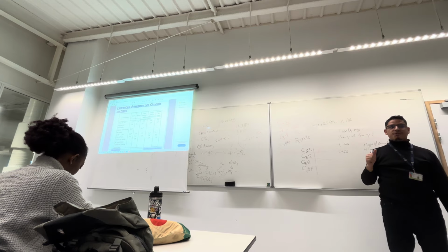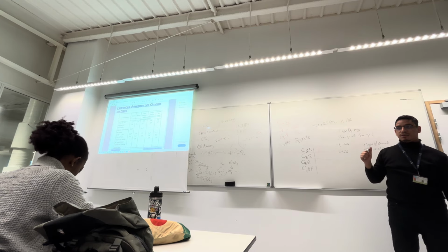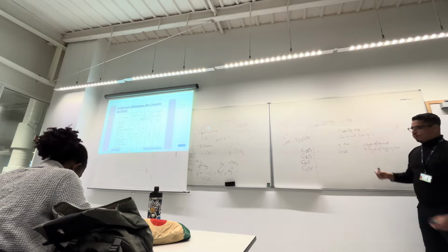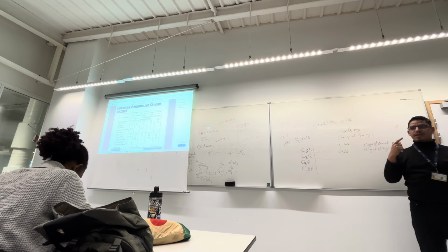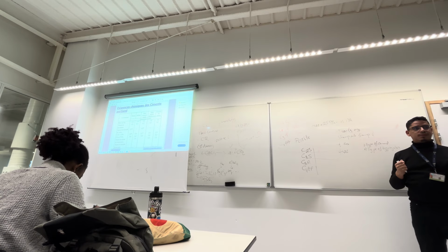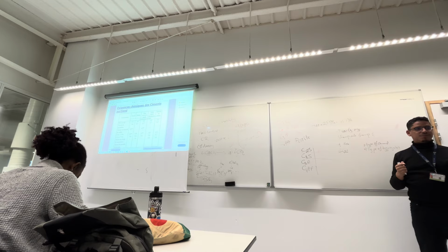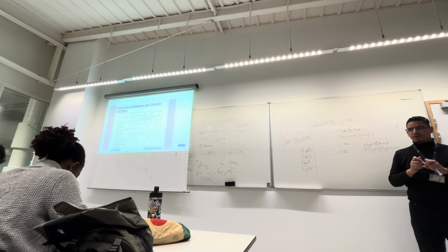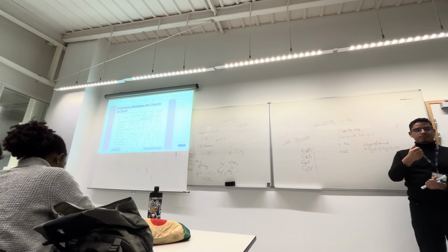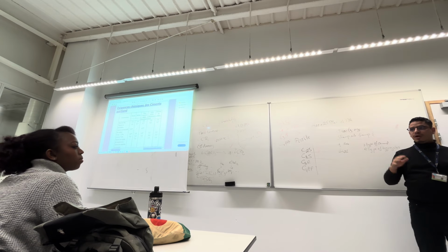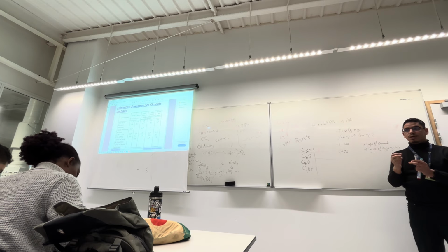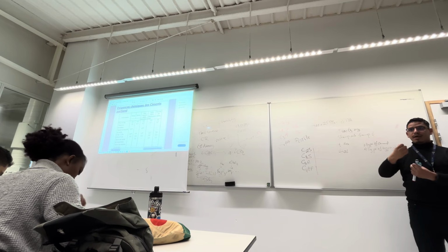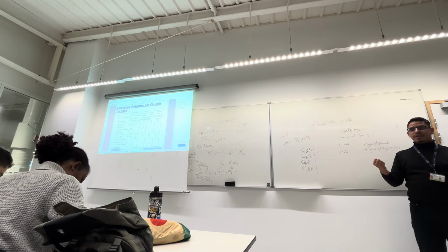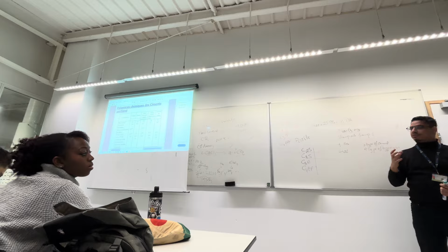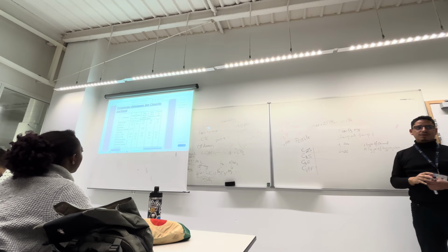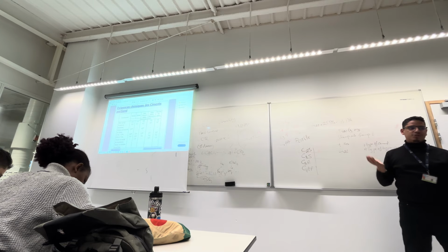the principal cause of crack is not the cement, it's aggregate, because when we apply the force for ordinary concrete, we can see that the cement is cracking. You understand a little bit? Say it again, please. We have concrete sample. We apply a load. For ordinary concrete, we have a lot of air voids in cement. So we have propagation of air void, and the concrete and the cement is cracking. In this case, for ordinary concrete, we should see a good cement.